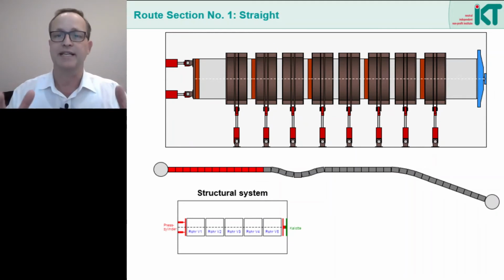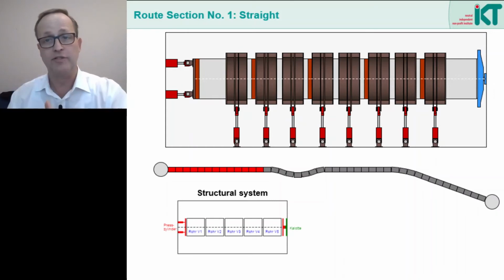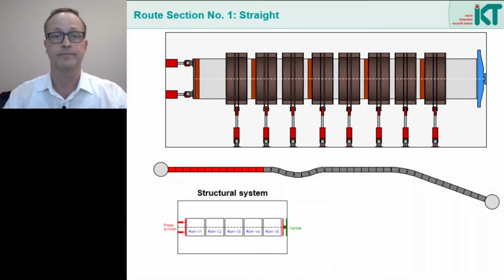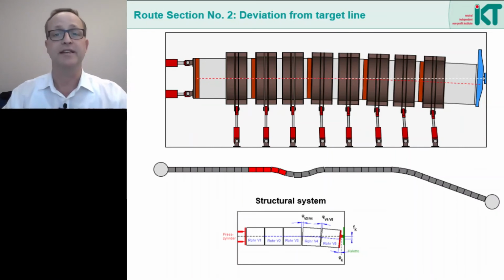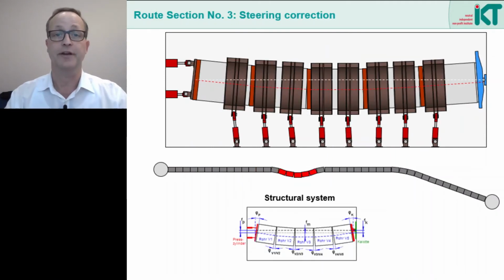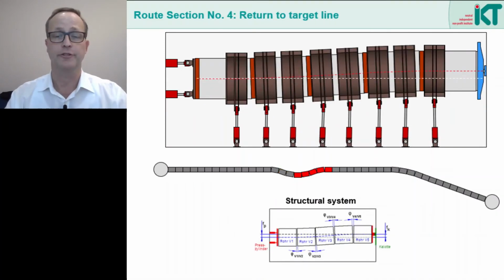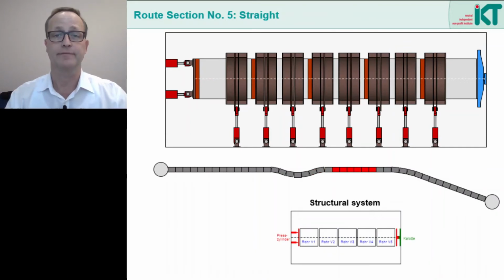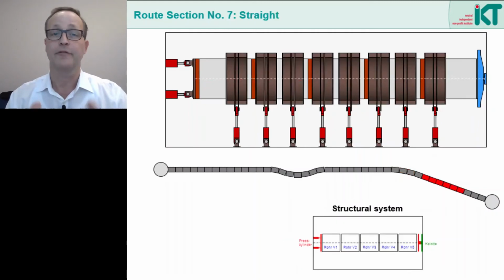Here at the top, we see the test setup and below it, the corresponding part of the route. And there is also a sketch for the structural system, which is simulated here. With a straight line, we started a total of 10 load cycles as average for the pushing of the pipe into the straight line. From the straight line, the route continued into the deviation from the target route. Then the steering correction, the return to the target route, and then the second straight line, a planned curve, and finally the last straight line. Of particular interest were the pipe stresses and strains in the planned curve shortly before the end of the pipe jacking route. In terms of statics, the curve is often the critical condition to which the entire system is dimensioned. That means the pipes and also the pressure transmission rings.